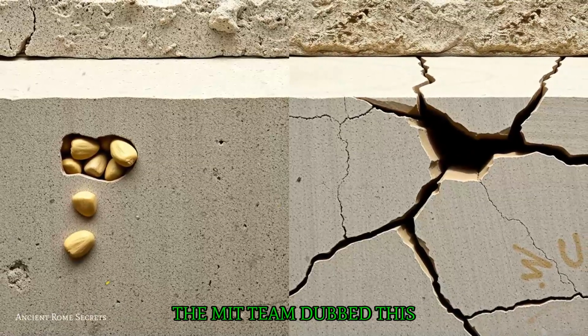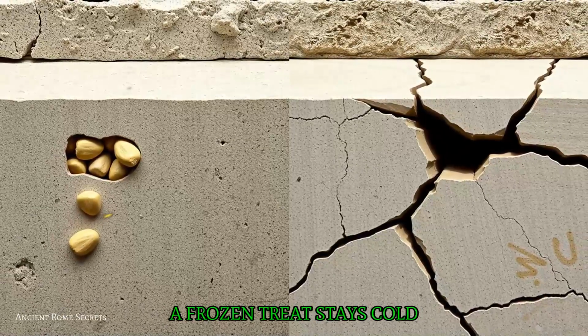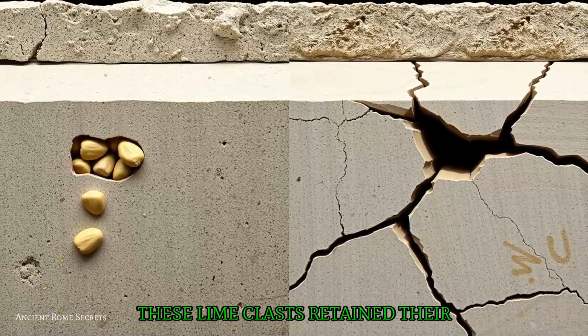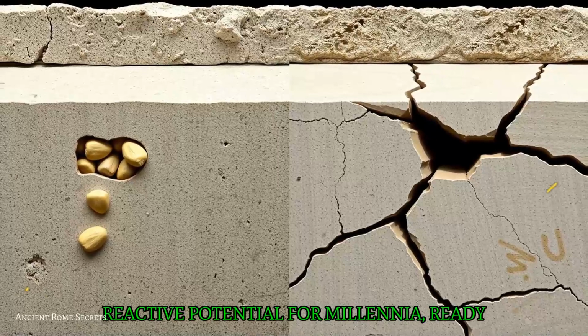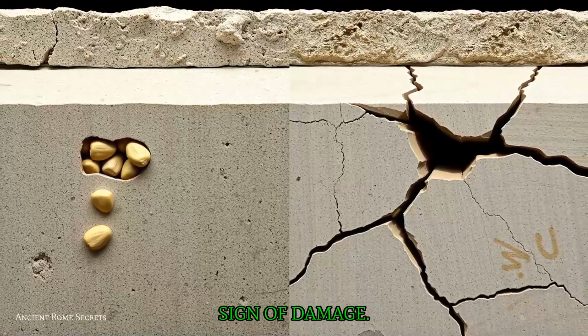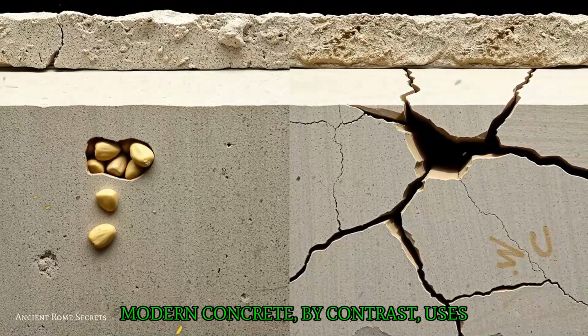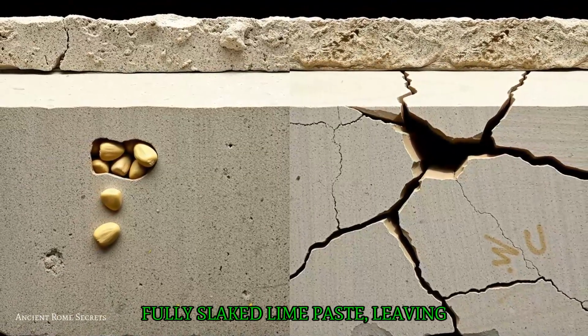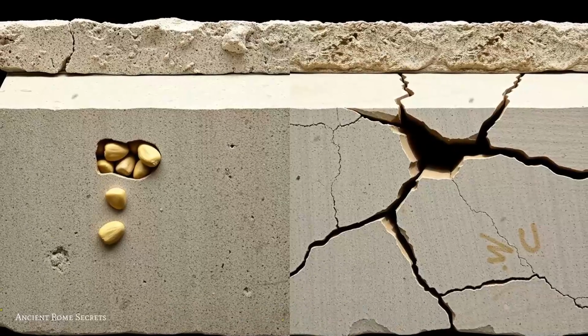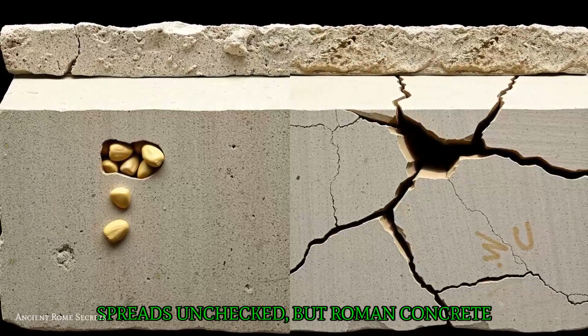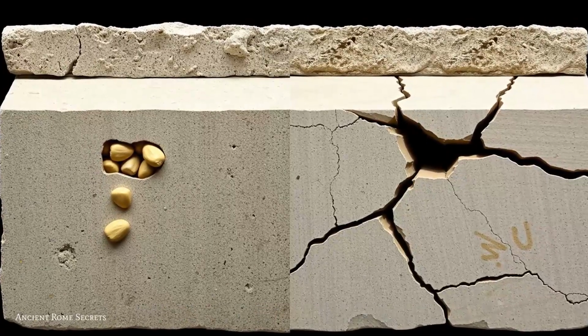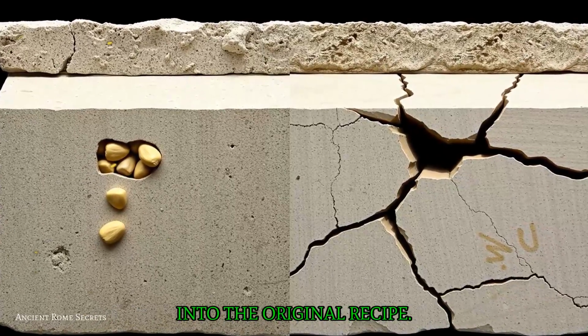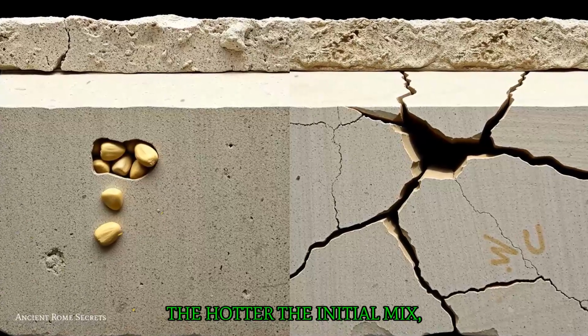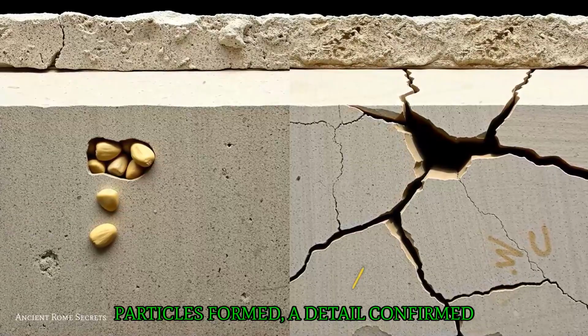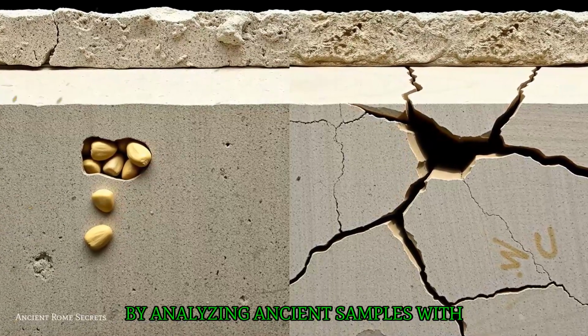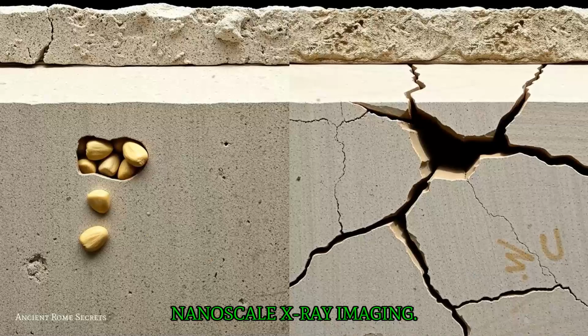The MIT team dubbed this the popsicle effect. Just as a frozen treat stays cold long after leaving the freezer, these lime clasts retained their reactive potential for millennia, ready to activate at the first sign of damage. Modern concrete, by contrast, uses fully slaked lime paste, leaving no reserves for future repairs. Once it cracks, the damage spreads unchecked, but Roman concrete had a built-in insurance policy, its healing capability embedded right into the original recipe. The hotter the initial mix, the more of these reactive particles formed, a detail confirmed by analyzing ancient samples with nanoscale X-ray imaging.